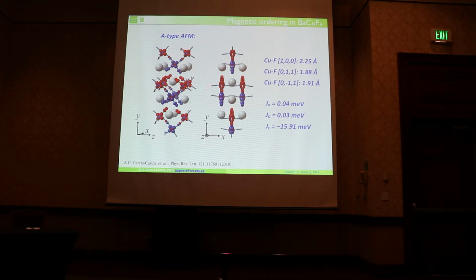So when we analyze more carefully the electronic structure, we can see that we have a strong Jahn-Teller distortion here due to the d9 occupation of the copper, and we have a dx²-y² type of orbitals. And look, for example, at the distances of the bonds for the copper and fluorine. This one is the longest one, it's close to 0.3, larger than the other ones, and that explains the magnetic ordering on this structure. And additionally, when we compute the exchange constants, what we realize is that the exchange constant along this direction is really strong, explaining as well the large antiferromagnetic Néel temperature.